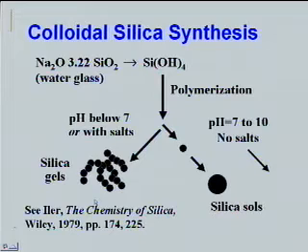If we decrease the pH value more, the silicate has less negative charge, so it's easy to collide and stick together. But if we control the pH level to a weakly alkaline condition, we can get the silicate sol. The silicate sol is more stable than the silicate gel.